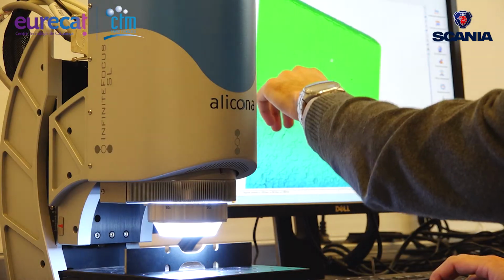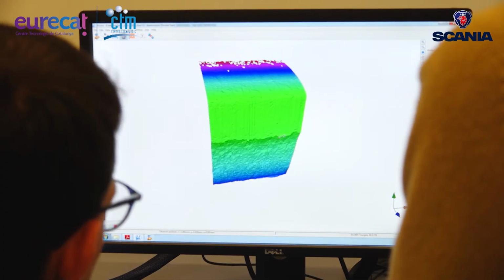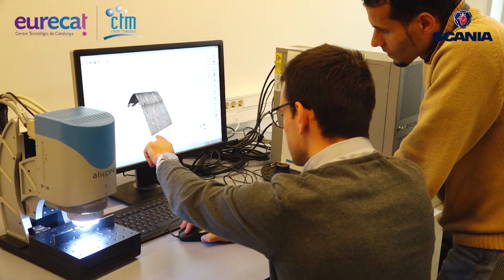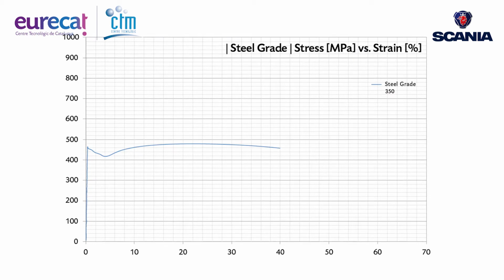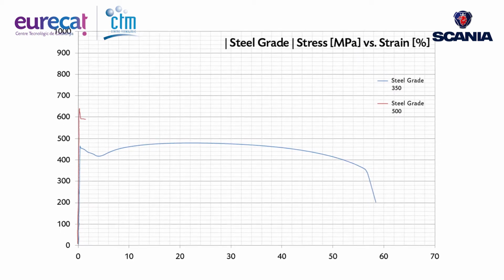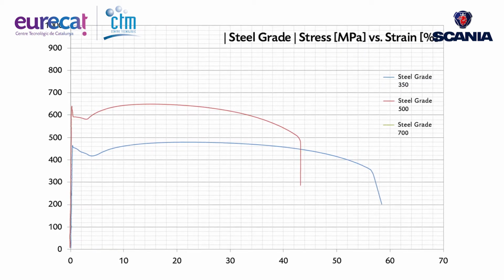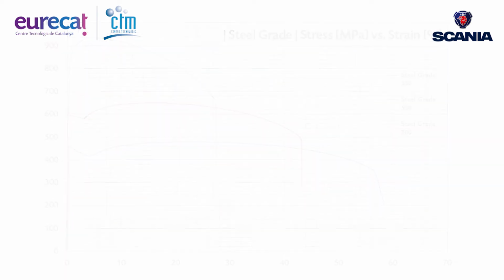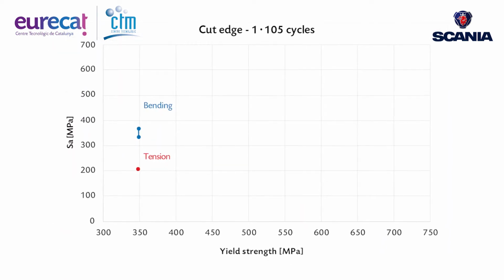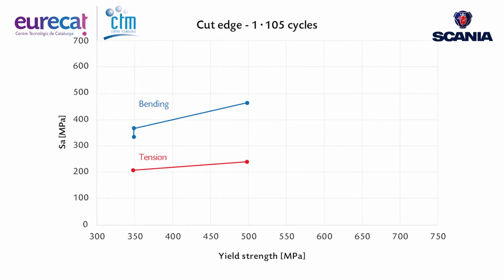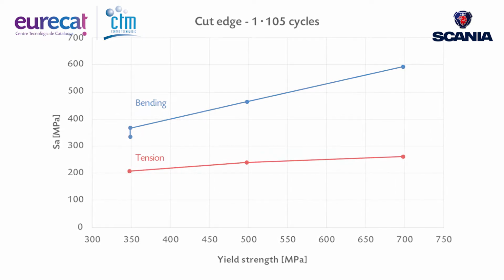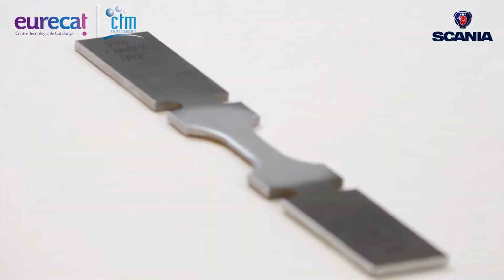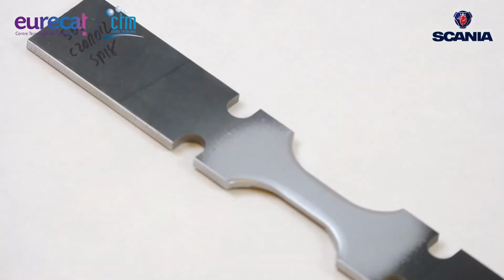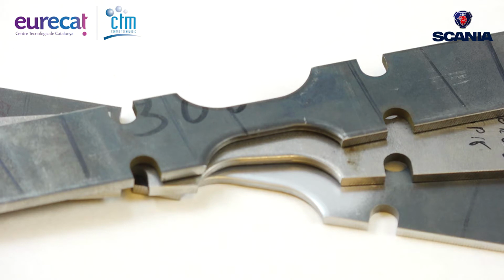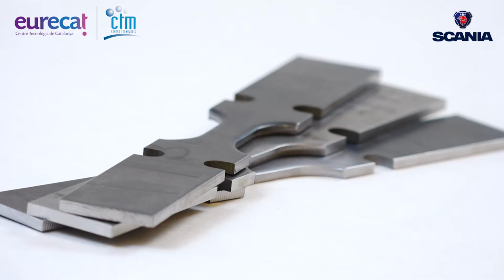After the test, an accurate study of fatigue fractures by scanning electron microscopy leads us to understand the edge behavior under bending fatigue conditions. The results obtained by CTM Eurecat jointly with Scania from all the tests mentioned before allow us to state that using higher steel strength, the fatigue limit is increased by 62% compared with the lowest steel grade under the same edge conditions. Fatigue life is highly influenced by stress ratio, and the blasting process improves the edge quality and fatigue strength by at least 10%.